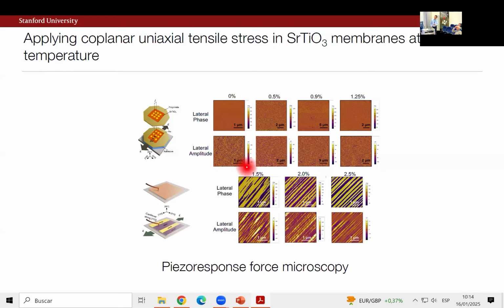So in this work, what I'm showing you here is piezo force microscopy. And this is literally just looking, you know, if you say, I don't see anything here, that's the point. Nothing interesting is happening. At room temperatures, we go from 0 up to over 1% strain. But suddenly we go from 1.25 to 1.5% strain. You see lots of signal and contrast in PFM, right? And so this signals the onset of ferroelectric domains.